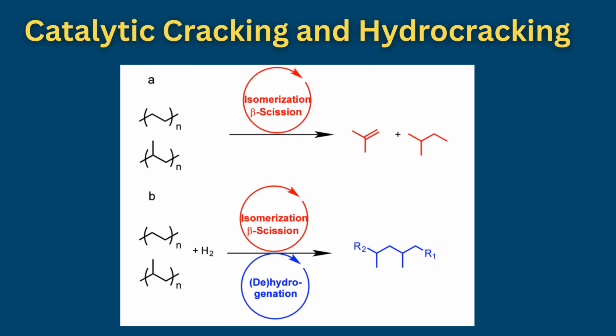Catalytic cracking and hydrocracking. Thermal pyrolysis proceeds via radical mechanisms at temperatures above 500 degrees Celsius. Catalytic cracking employs acid catalysts at somewhat lower temperatures, greater than 400 degrees Celsius, generating isoalkanes, alkenes, cycloalkanes, and aromatics. Hydrocracking combines acid functionality with hydrogenation, dehydrogenation components under high H2 pressure. It proceeds exothermically at lower temperatures and produces narrower product distributions, primarily isoalkanes.